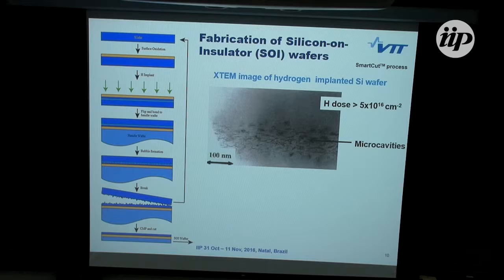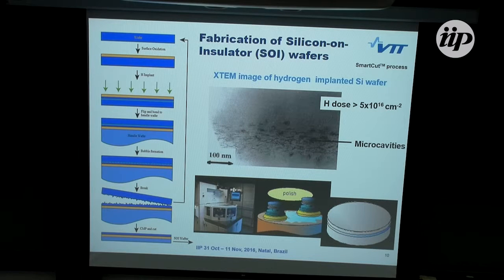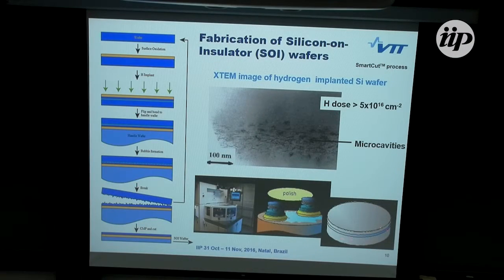At early times, there was a process where, instead of hydrogen, they implanted oxygen and then annealed it, and then it formed silicon dioxide in between. With this process, the typical thickness range is from 200, 300 nanometers down to about 10 nanometers thickness of an already fabricated wafer. So the wafers look like this. There's a handle wafer, silicon, and then a silicon dioxide layer, this film there, and then the top layer, which is the device layer.